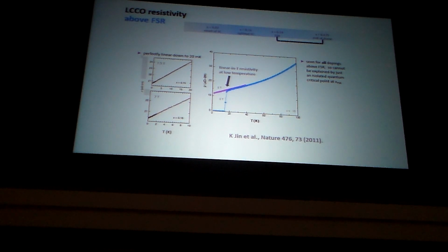And why it should occur over a range of doping is also unexplained. There are ideas that something called quantum criticality. If you have, let's say you go from a metal to an antiferromagnetic state, you can have at T equals 0 something called a quantum phase transition. So you go from the metallic state to the antiferromagnetic state at T equals 0, and at the point where that happens, a quantum critical point, you can then have fluctuations, quantum fluctuations associated with that point, and that can lead to a T-linear resistivity.